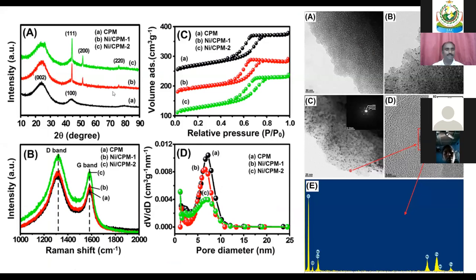Initially, the prepared material is characterized by the X-ray diffraction pattern. You can see the bare carbon porous material, and nickel 2 plus doping in different ratios. I labeled them as nickel CPM 1 and nickel CPM 2, which have different ratios, 0.5 and 1.8 percent of nickel 2 plus. And you can see the nickel peak has emerged in the carbon material. So that indicates nickel is present in this carbon material.